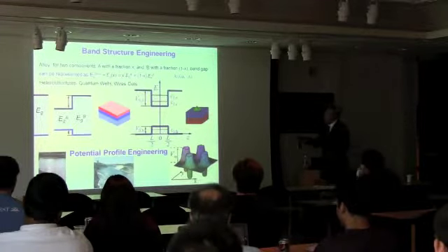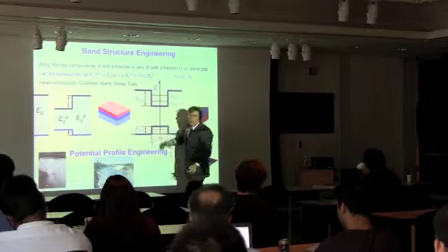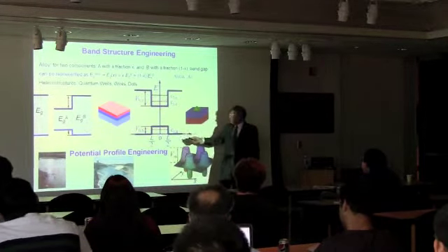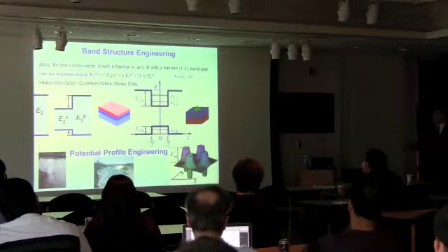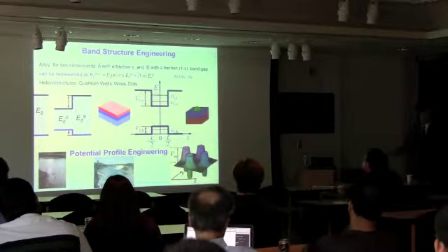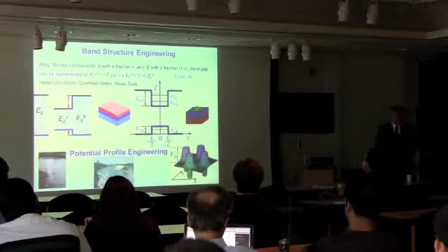And then of course if I do confinement in this direction as well, now it will be a very thin wire, and if it has very small dimensions, it will be a so-called quantum wire. Now electrons can move only in one direction. Finally, I can make a very small material, like a cluster, as shown here, and this will be so-called quantum dots. Why quantum dots? Because it becomes like an artificial atom, and now the motion of the electron is confined in three directions.